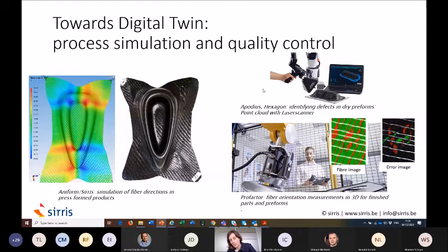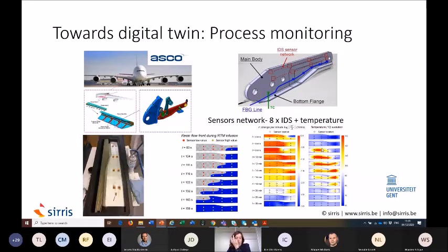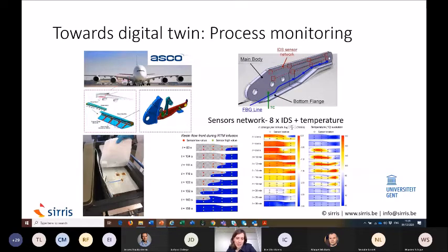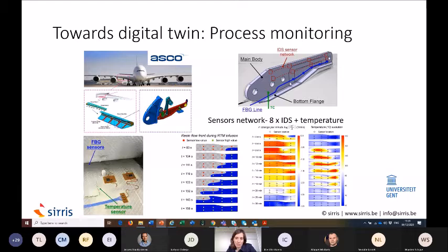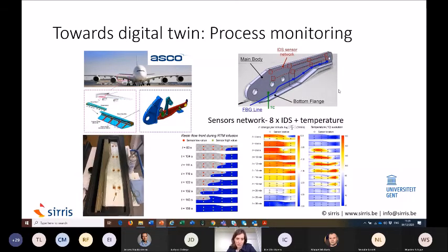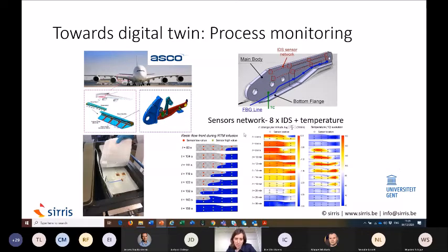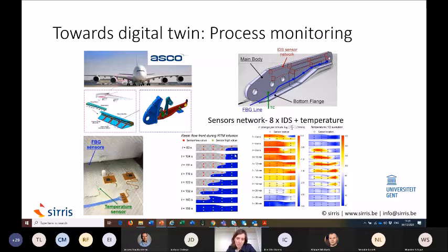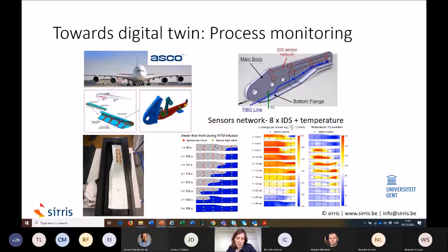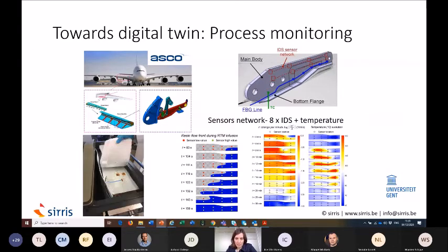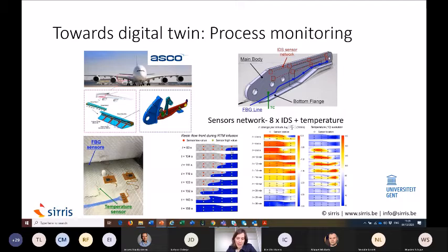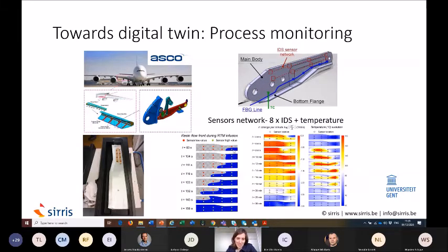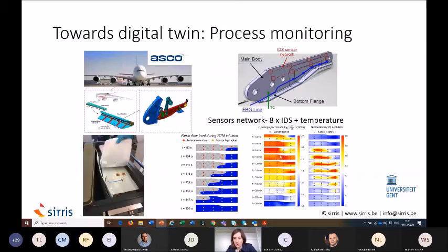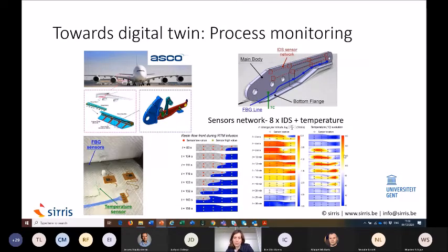On the other hand, we have a lot of technologies emerging on quality control. It's really seeing where the fiber is in your products after manufacturing. There are several technologies available. One other emerging technology is incorporating sensors, fiber Bragg sensors, capacitive sensors. This was a project that was done together with the University of Ghent, where we looked at the infusion strategy for RTM products, and with the fiber Bragg gratings, you can very nicely see when there is resin at a certain time, and you can also monitor the cure of your product very well.